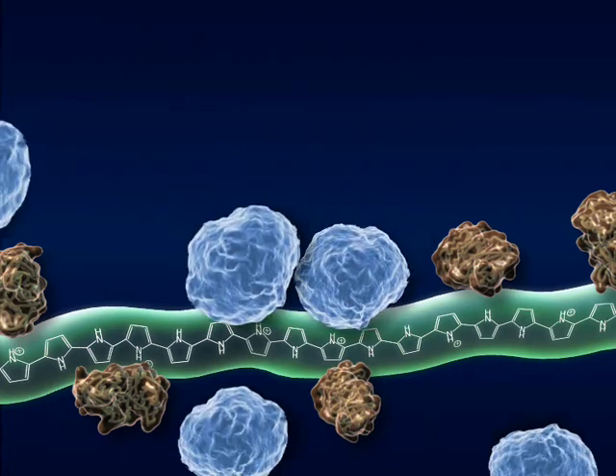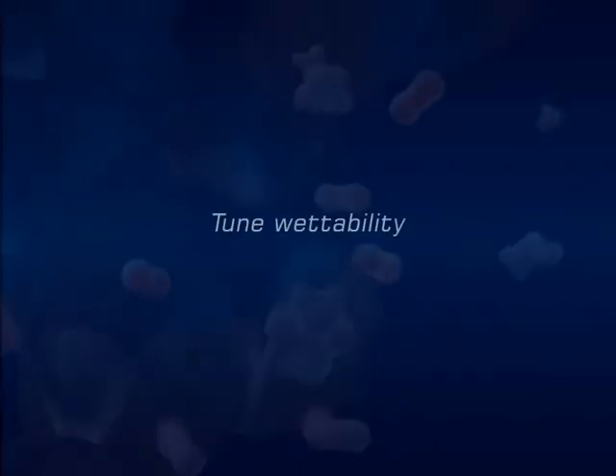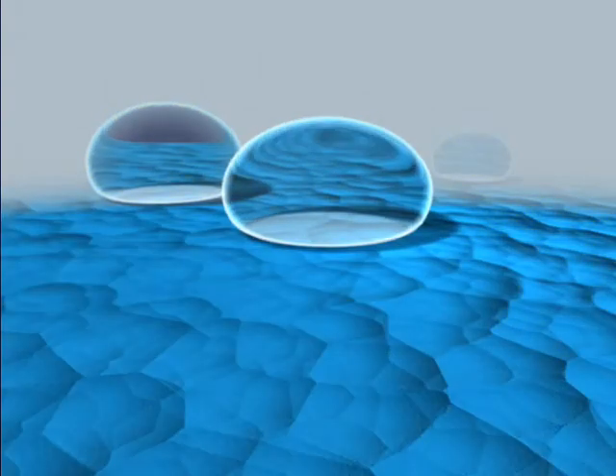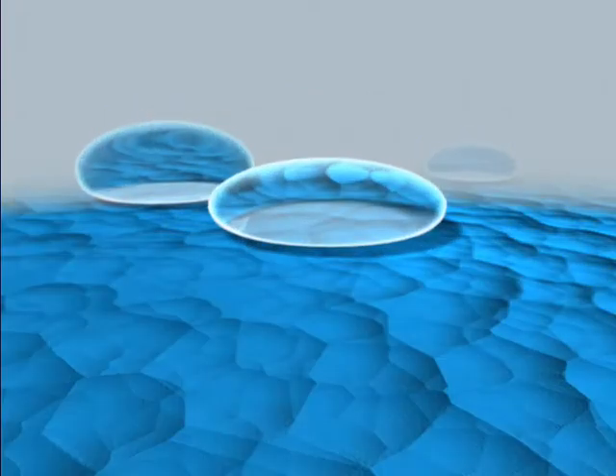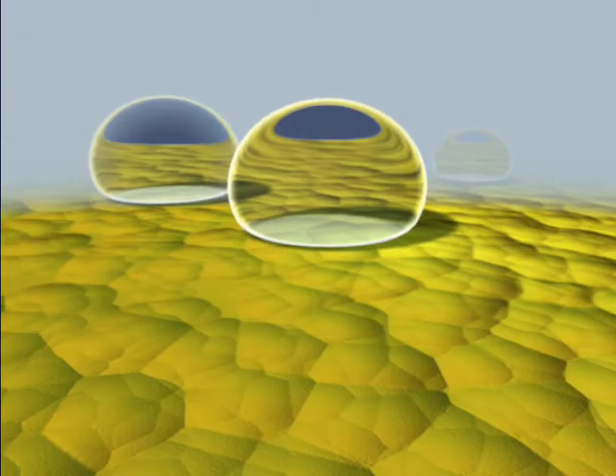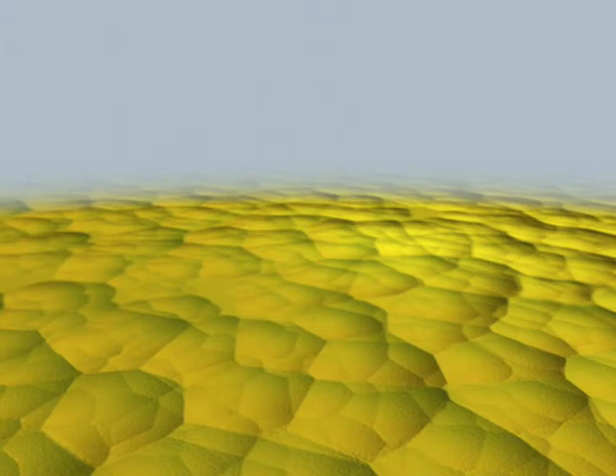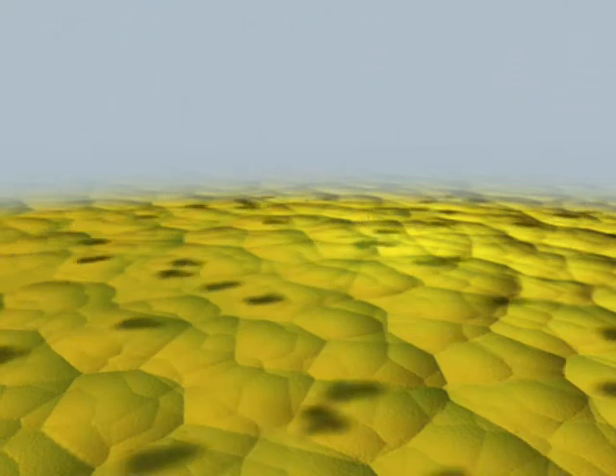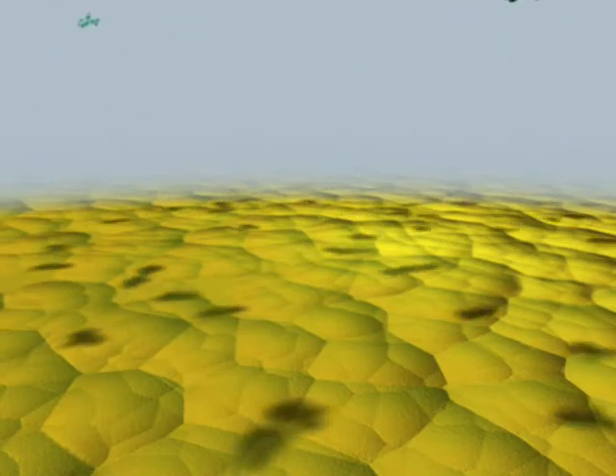To provide further control over the development of the electrode cellular interface, the properties of organic conducting polymers can be tuned in situ. For example, electrical stimulation can be used to induce significant changes in surface energy, giving us the ability to tune interactions with water and other biologically significant molecules. The release of biologically active molecules incorporated into the polymer at the point of synthesis can also be initiated by electrical stimulation, enabling control over the chemical environment that will determine the nature of the electrode cellular interface.